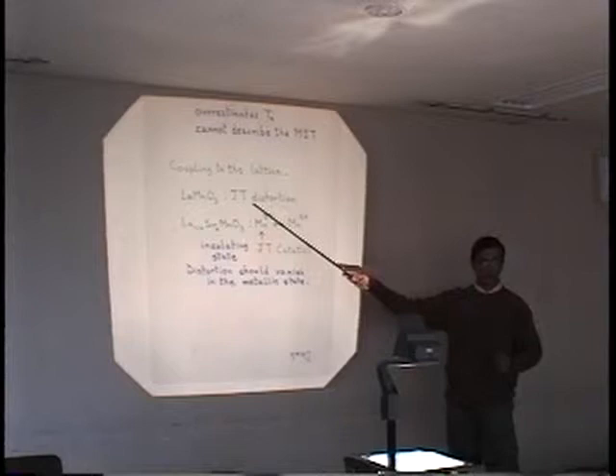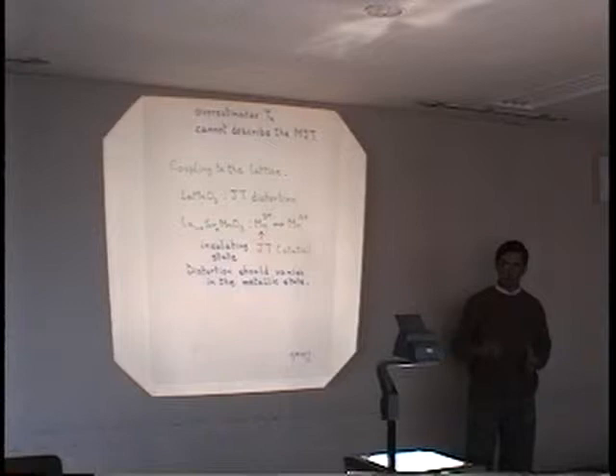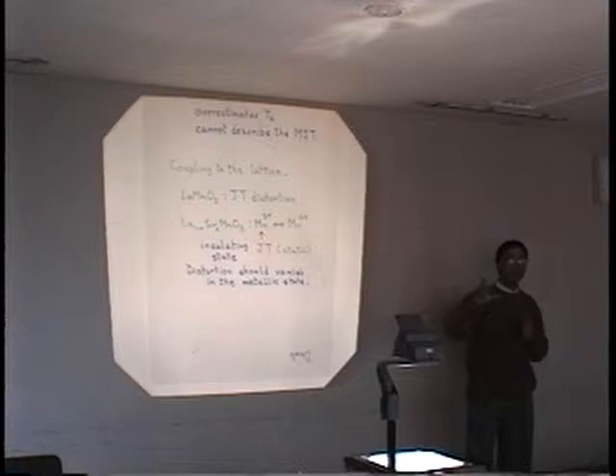It has been known that when you dope holes into the system, like strontium in lanthanum, this Jahn-Teller distortion, static Jahn-Teller distortion disappears. So people have talked about dynamic Jahn-Teller distortion because from there you can easily get a coupling between the electronic states and the lattice vibrations.